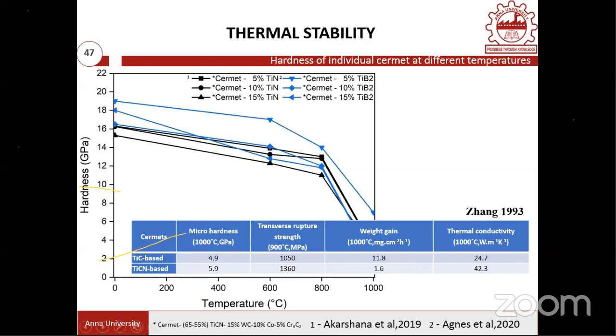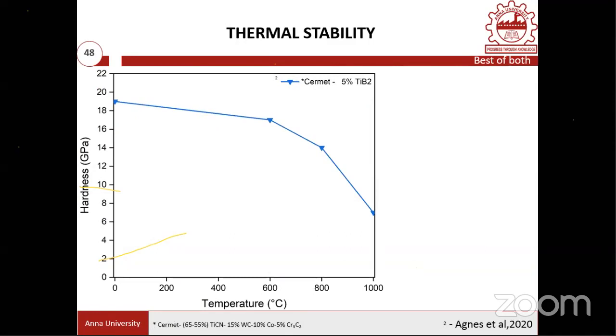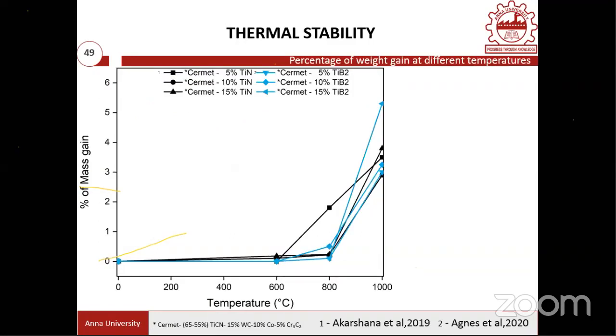Okay, now for our composition, if you look at the hardness value after heating for 4 hours at 1000 degrees centigrade, the hardness value is close to 7 GPa. Okay, so even at 800 degrees centigrade, the value is close to 15 GPa. So the first curve, which has the TiB2 content, is really a good CERMET composition, which is superior to the available literature value. Okay, so this is one which is showing good improvement. And another, the mass gain.